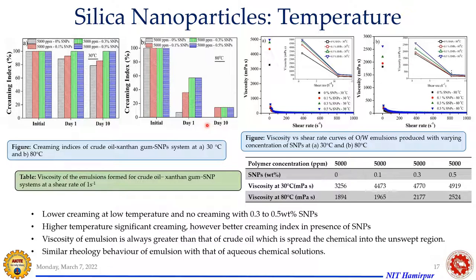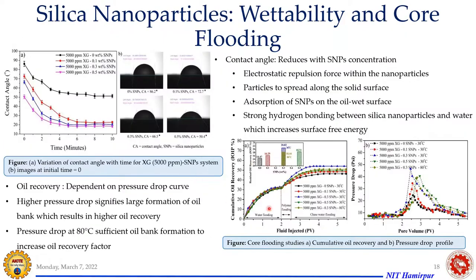To validate this result, we have done flooding experiments for all the nanoparticle concentrations, and then we tried to analyze what is the best outcome for higher recovery with the best possible optimum slug for this nanofluid flooding condition. So you can see here, when we have only polymer flooding, nothing else, we have achieved an oil recovery of around 14.5% at room temperature, with no nanoparticle concentration.